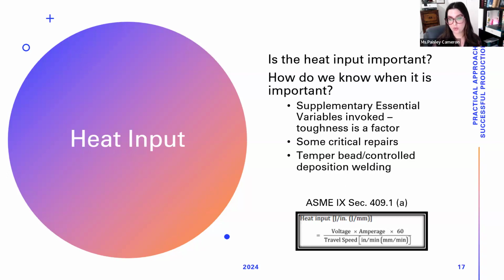Heat input can also be important for specific critical repairs, even if it is base metal, carbon steel boilerplate. Due to the thicknesses, or the piece of equipment, or the aging or service requirements of that equipment, it can be important to monitor your heat input. Duplex stainless steel, very important for your heat input to be controlled. Temper bead or controlled deposition welding, as we talked about, is very, very important for your heat input.